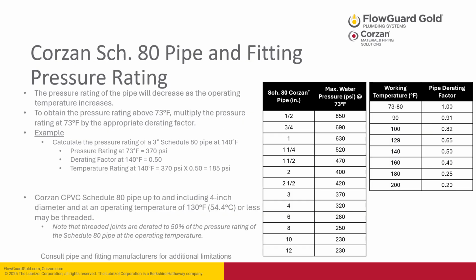Corzan Schedule 80 pipe and fittings are an iron pipe size schedule system. Because of this, the pressure rating of the pipe will not only decrease as the operating temperature increases, but it will also vary by size. To obtain the pressure rating at elevated temperature, multiply the pressure rating at 73 degrees Fahrenheit by the appropriate derating factor. So as an example, for a 3-inch Corzan pipe at 140 degrees, you'll begin by taking the pressure rating of 3-inch pipe at 73 degrees, which according to the first table is 370 psi. Then you'll multiply it by the derating factor at 140 degrees Fahrenheit, which is shown as 0.5. 370 psi times 0.5 equals 185 psi, which will be the pressure rating for 3-inch Corzan at 140 degrees Fahrenheit.